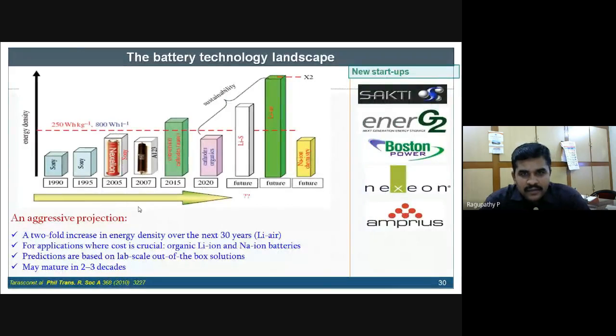And this is the entire battery technology landscape. We started with Sony, that is lithium cobalt oxide. During the 90s the energy density was around 100 watt-hour per kg. Then there is a gradual change in the chemistry from lithium cobalt oxide to spinel and lithium iron phosphate, and these are the players making use of these kinds of materials. Now, see the organic batteries, which are also taking up another area. More importantly, lithium-air and lithium-sulfur are going to be the major players in this storage technology.